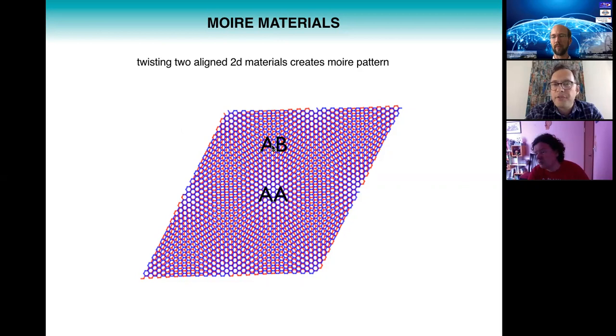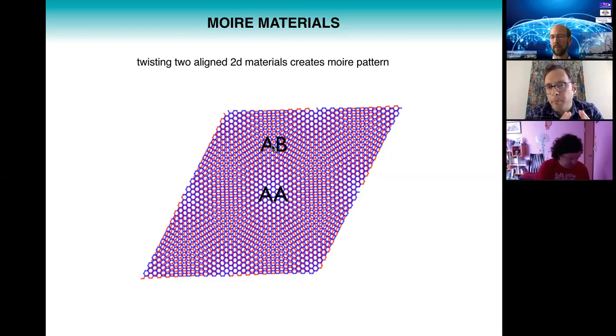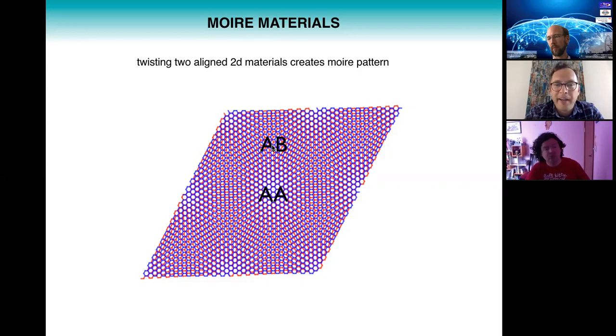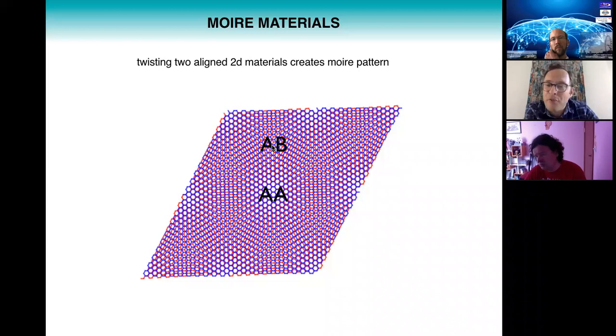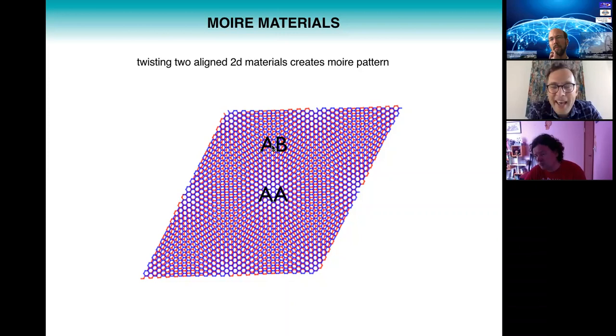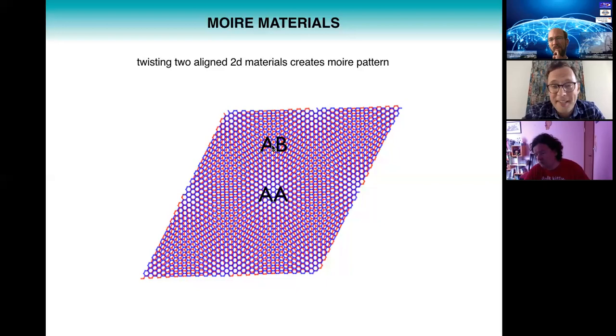There are other ways of creating moiré patterns: you could put one-dimensional polymers onto a graphene crystal, which creates a different kind of moiré pattern. You can also take two different 2D materials — a hetero-bilayer, for example graphene and hexagonal boron nitride — put those on top of each other, and you will find a moiré pattern without a twist that arises just from the mismatch of lattice constants. One of the pleasing aspects of these materials is that they are rather beautiful, and in fact we collaborated with the Royal Society of Sculptors at the Great Exhibition Road Science Festival to demonstrate the interplay of scientific interests and beauty.